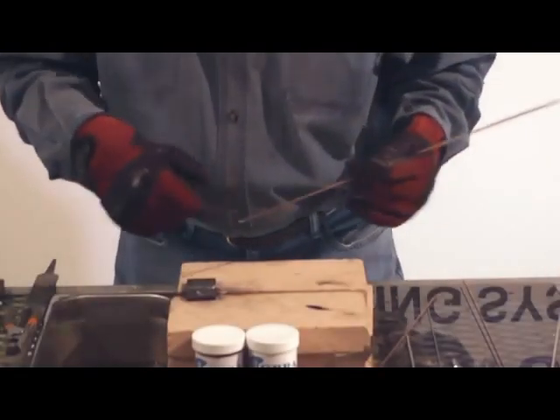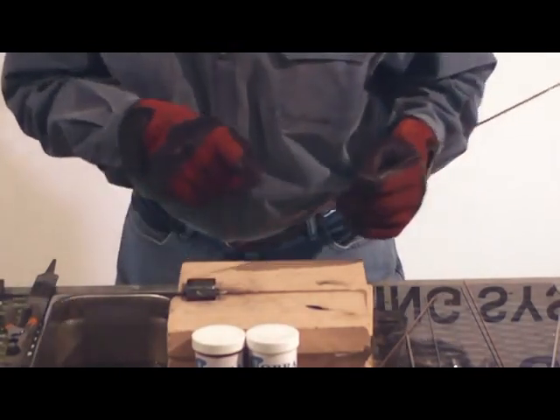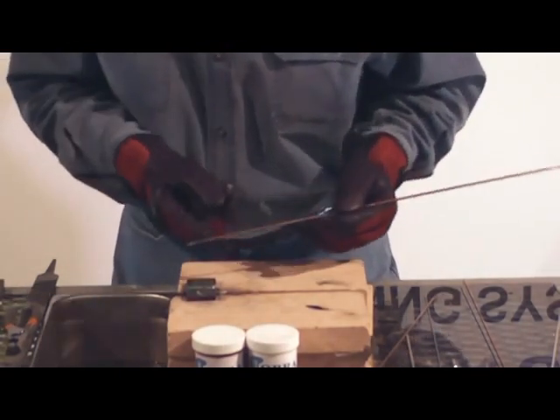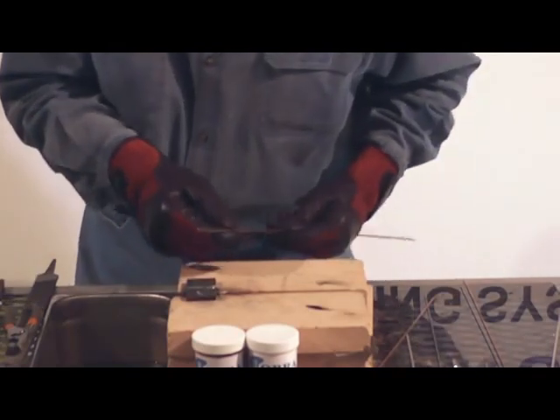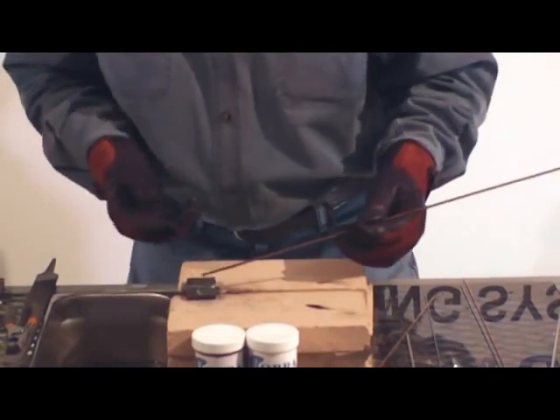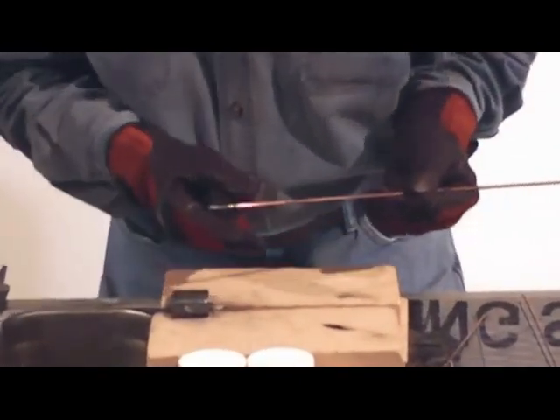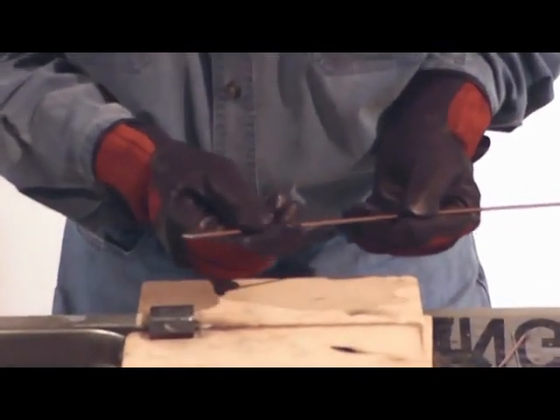We're getting ready to weld some quarter-inch steel. I've also beveled. Remember, anything over one-eighth of an inch, you want to bevel, you're going to have to use a thicker rod. This is a one-eighth E70S. You can use your stick electrode, 7018, 6010, 6011. Just knock the flux off. Remember, welding thick metal, you've got to use a thicker rod for it.